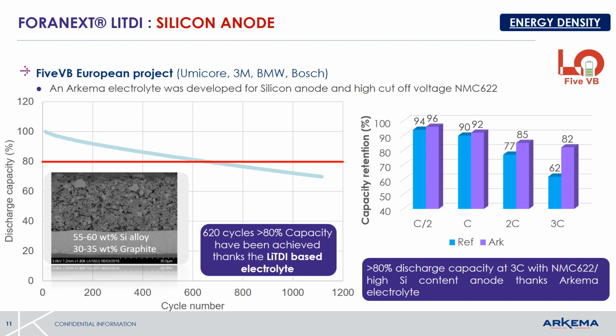To increase the energy density, LiTDI is useful to stabilize the SEI on silicon. A few years ago, in the frame of a European project, we developed an electrolyte to improve the lifetime of batteries based on NMC622 and 60% in weight of silicon on the anode side. Besides the lifetime improvement, the LiTDI-based electrolyte enables to improve the discharge power performances.